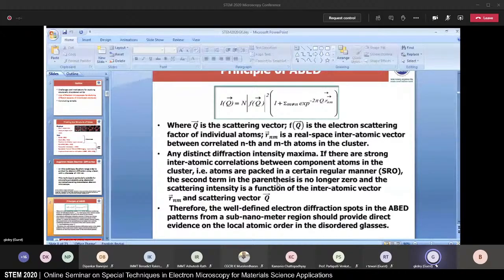So if atoms are packed in a certain regular manner, you will get a peak. And the intensity of that peak will depend upon R and Q. So this term here will no longer be zero, and you will get a diffracted beam. The intensity of the diffracted beam will also depend on the orientation of the two atoms with respect to each other, because that is how constructive interference will happen. So that will give rise to diffraction. This is the principle of ABED.